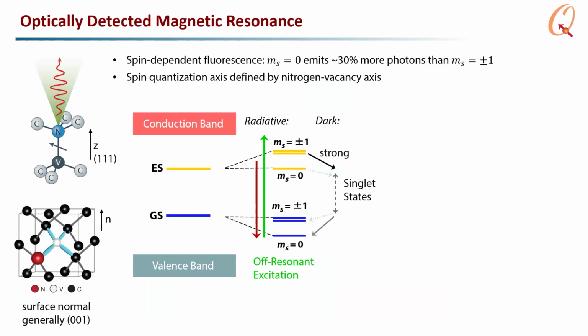Okay, so the beauty of the NV center in diamond is that the spin of the NV center can be read out through fluorescence. So the NV center consists of a ground state spin triplet and an excited state triplet within the band gap of diamond. So it's a deep defect. And what you do is you can shine green laser light on the NV center and it will emit red laser light. So phonon downshifted spectrum.